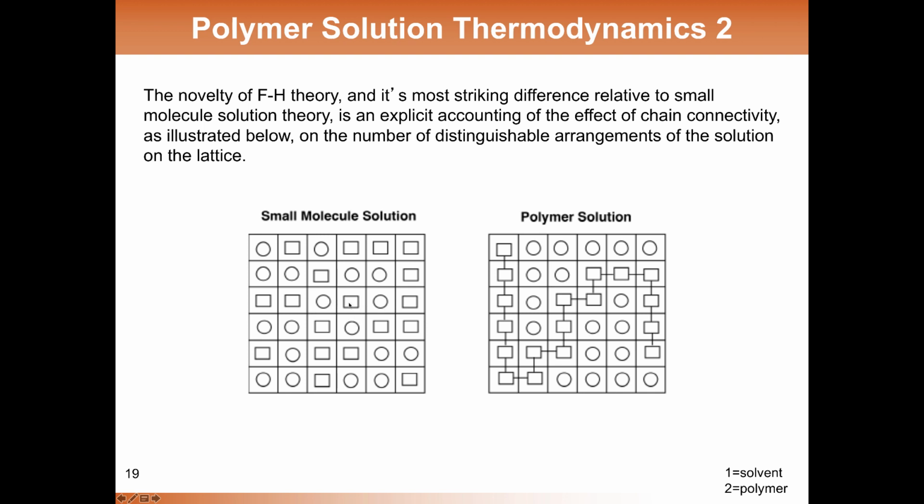And in fact, this is what we routinely observe in polymer science: if you have a monomer that is soluble in a solvent and you start to polymerize the polymer in that solvent, in many cases the polymer will eventually phase separate out of solution. It doesn't want to be dissolved in that solvent the way the monomer would.